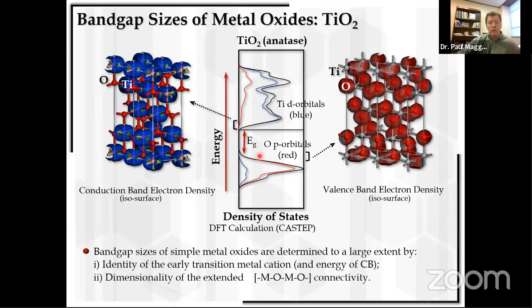And what's more, if you want to close this gap down, close it down from being absorbing in the ultraviolet region to absorbing in the visible region, you really have no opportunity to do that without adding now a third element, something that can come in and insert filled energy levels here and shorten the gap between this forbidden region and the conduction band here.